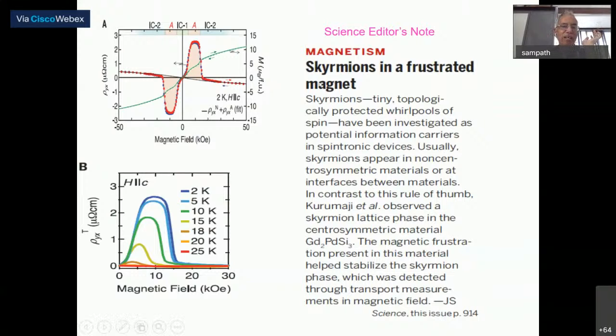Look at the Hall data here. Hall resistivity is exactly the same as what we have reported in our paper here. So this is a topological Hall effect, which is now very well recognized in current literature. And the science editor has clearly written down here that this was detected through transport measurements in magnetic field, that is Hall effect. So it's very pleasing for us to see that something which existed 20 years ago, Tokura picked up and brought out to limelight.